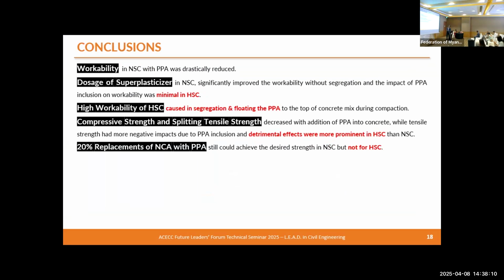As I explained throughout the presentation, the workability reduction is there because we haven't post-processed the plastic waste. On the other hand, by incorporating the superplasticizer, we can increase the workability. But when it comes to normal strength concrete, the inclusion of the superplasticizer should be mindful because it was giving a drastic increase. And when it comes to the compressive strength, there are some detrimental effects.